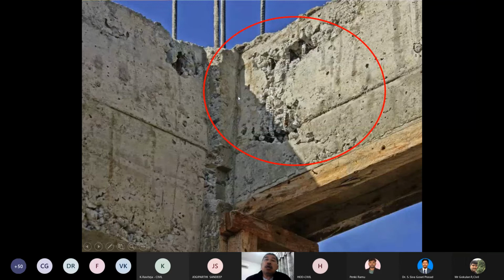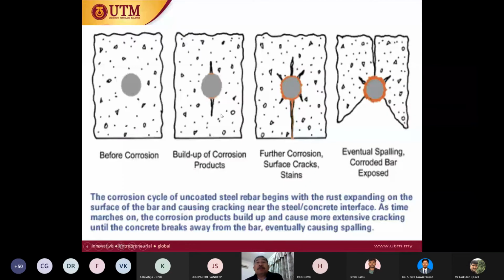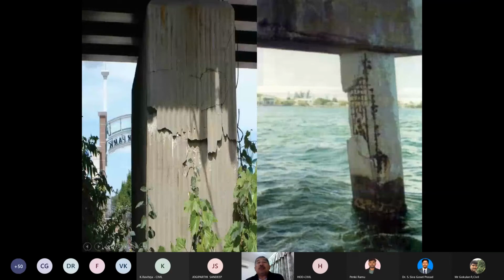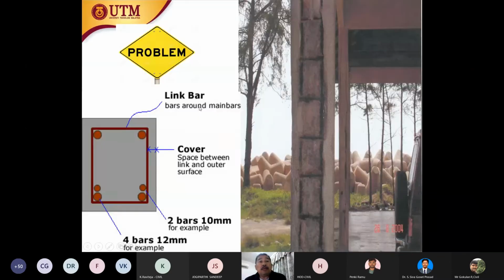If this happens when you demolish the formwork, we need to do proper repair. Proper repair methods. If not, then we have a corrosion problem. Why? Because once the reinforcement starts to corrode, it will induce internal stress in our concrete. Once the internal stress is very high, the concrete will crack. Once the concrete cracks, it starts to spall. Okay, so these are some of the problems. On the right side is due to corrosion. This one is probably due to overloading.